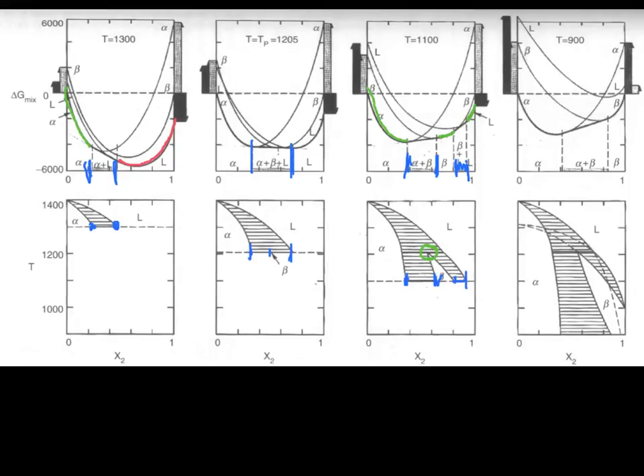So, let's look at a couple of examples of phase diagrams which show peritectic reactions. And I guess I should point out here that the sort of signature of the peritectic is that, on cooling, you go from alpha, a solid, and a liquid, to a different solid phase. So, this is the reaction which is occurring right here, right? We're going from the alpha and the liquid into the beta phase.